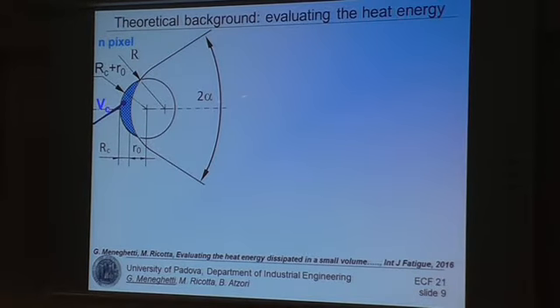Now, we have to evaluate the heat energy dissipated in the structural volume. So, imagine you take a picture with the infrared camera at the notch tip. We have defined the structural volume size. You have a number of pixels inside the structural volume. Imagine defining the mean temperature inside the structural volume. It has an evolution during a fatigue test.